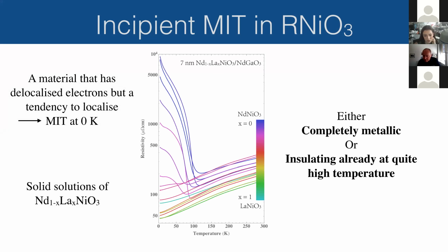So the first thing that we thought was that the symmetry might be important. Neodymium nickelate has orthorhombic symmetry, and lanthanum nickelate has a rhombohedral symmetry. So at some point during this solid solution phase diagram, you should go from one symmetry to the other, and maybe this is suppressing a metal insulator transition that would otherwise have been much lower in temperature. That was one thought. It doesn't really seem to be the case.